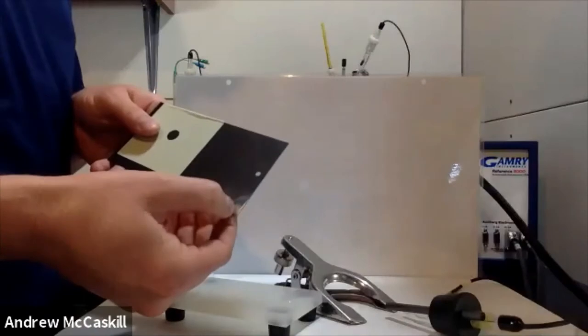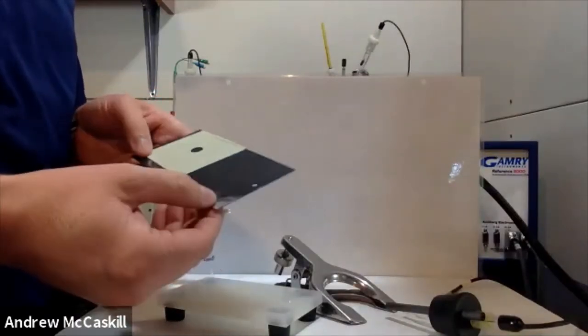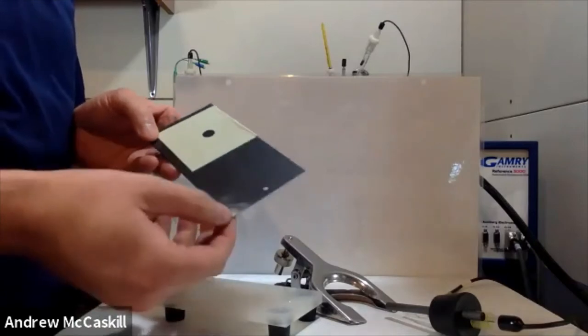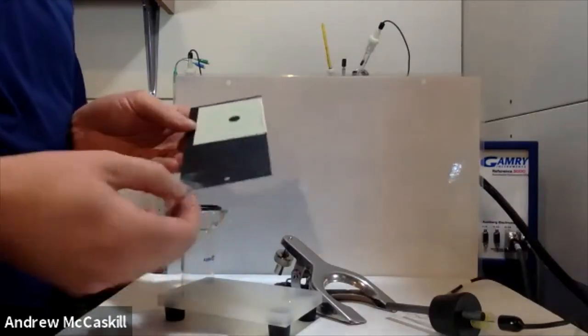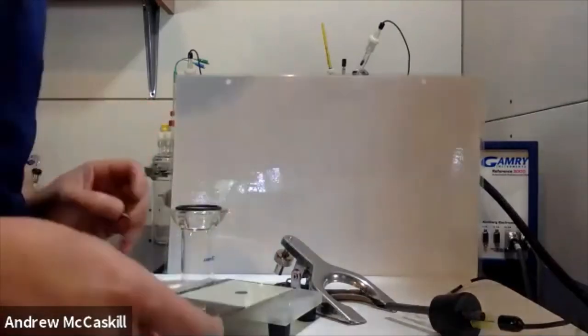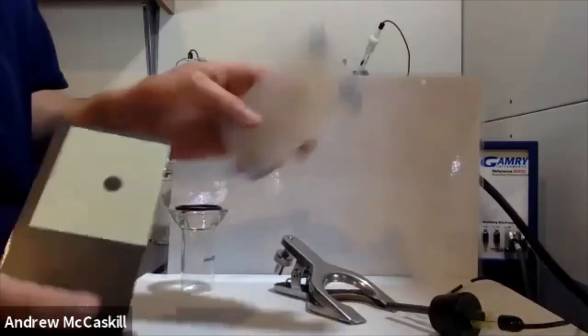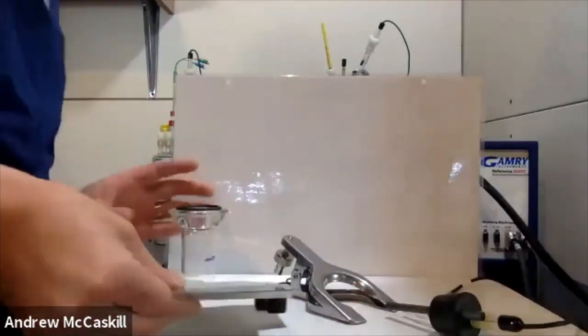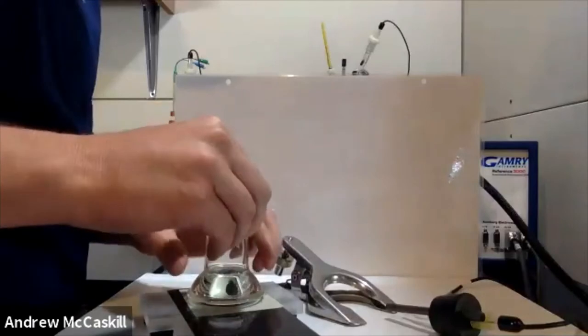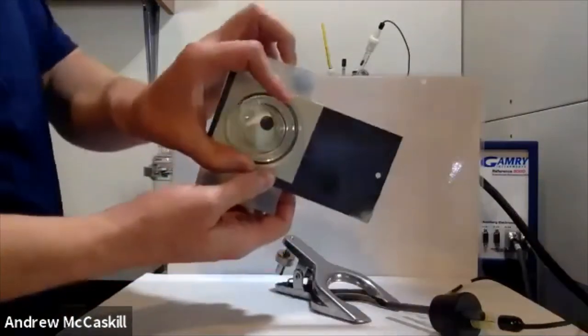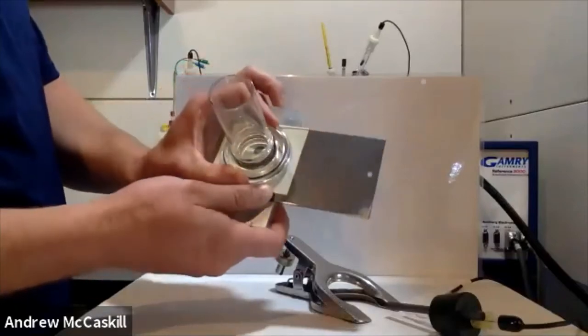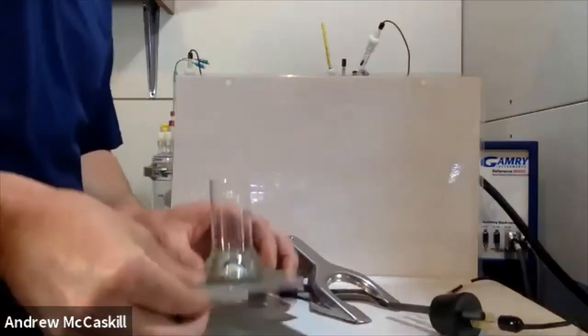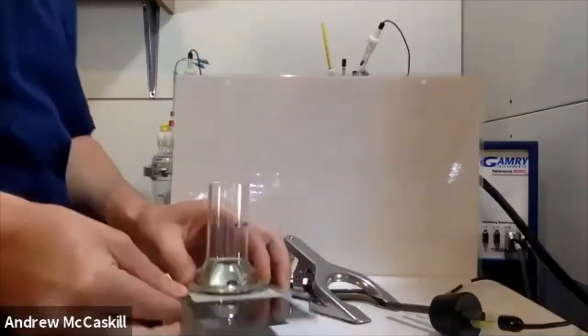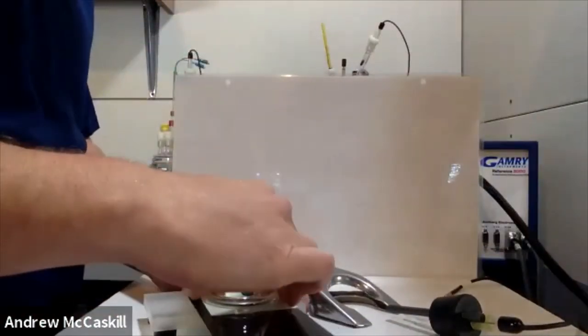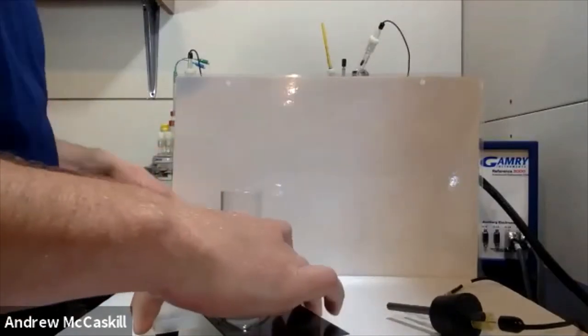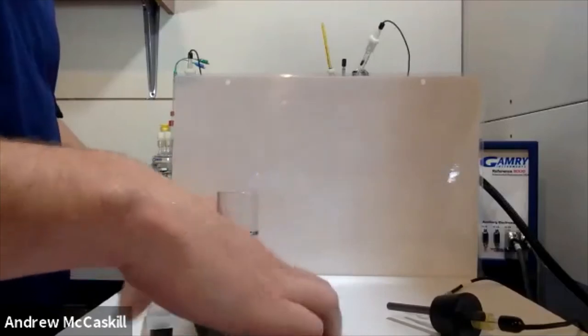So what I did first is just kind of scratch off the edge right here to expose some of the substrate. If you're testing on coated samples like this, make sure you get the exposed metallic substrate. Don't try to connect your cables to the coating. You're going to see that your data is not going to be very good if you do that. But we just have our base here. I'm going to set the coated sample right there. O-ring sits on top, like so. And you can see our exposed area of the coated sample down below there. And so right there, that's our working electrode that we're looking at down on the bottom, and the base of our cell at the same time. So we have this clamp to create that seal on the bottom of it here.